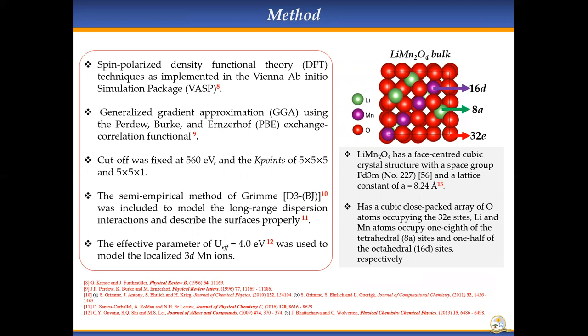In this work we use spin-polarized density functional theory as implemented in the Vienna Ab Initio Simulation Package. We use the generalized gradient approximation using PBE-PAW as the exchange-correlation functionals. The cutoff energy was fixed at 560 electron volts, and the k-point grid was 5x5x5 for the bulk and 5x5x1 for the surfaces. We also included the semi-empirical method of Grimme to model the long-range dispersion interactions. Due to the localized 3d manganese electrons, we employed the U parameter of 4.0 electron volts.